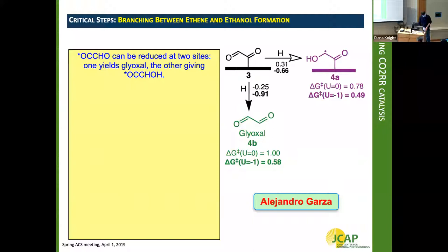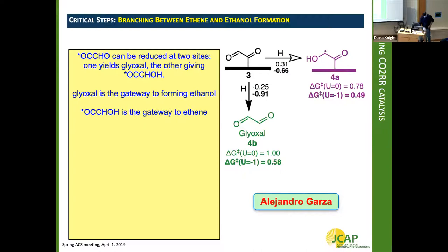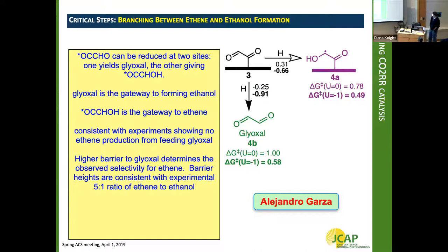And the important thing is that glyoxal is the gateway to forming ethanol, and 4A is the gateway to forming ethene. And this is consistent with experimental data. Now, the delta G daggers here at minus one volt are about 1/10 of a volt in favor of going down the ethene pathway. And that is consistent with an experimental ratio of 5:1 ethene production to ethanol production on copper 100.